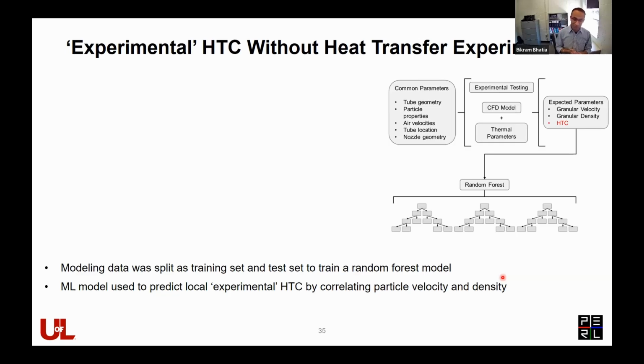So what we really wanted was the heat transfer coefficient from our experiment, and we argued that okay, the model is not high fidelity enough, but it does capture the basic physics of the particle flow for the two-phase fluid flow around the tube wall. And so what we did was we input tube geometry and other parameters like air velocities, as well as the granular velocity and granular density that we got from the momentum part of the model, by solving the momentum transport equation. And as the output, we gave the heat transfer coefficient. And so we had several million data points that we got from this quick simulation that we could do.